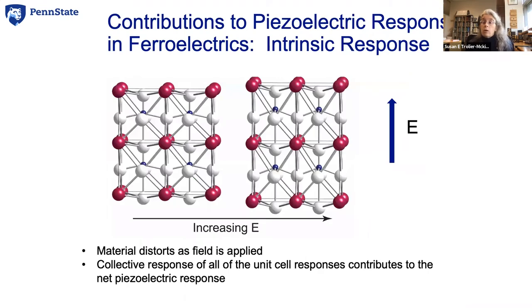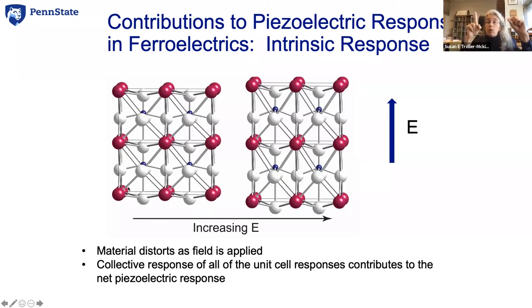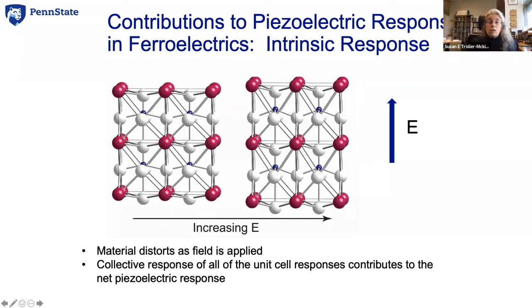How can we take this material and make it change shape with an applied electric field? In this volume of material, all the titaniums were displaced in the up direction, so I have a polarization in the up direction. When I apply an electric field in the up direction, the whole unit cell keeps getting taller and skinnier as that atom moves further and further off the center of the unit cell. That change in shape is one origin of what's called the intrinsic piezoelectric response.